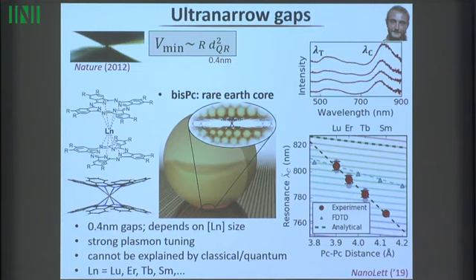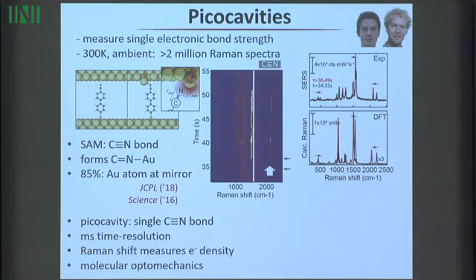And the problem is that we cannot solve both the quantum mechanics of electrons in this system and in the gold system simultaneously, so that we can do both classical and quantum together. We should be able to just do the full quantum. If I'm doing a standard DFT calculation and an advanced one where I'm trying to include with this molecule gold atoms, I get to a nugget that's about 1 nanometer. And my 1 nanometer of gold is not sufficient to understand the electromagnetism that's going on here. So you have to always have a boundary between the quantum bit of the problem and the classical bit of the problem, and nobody knows where to put that boundary or how to make it work. So these are problems.